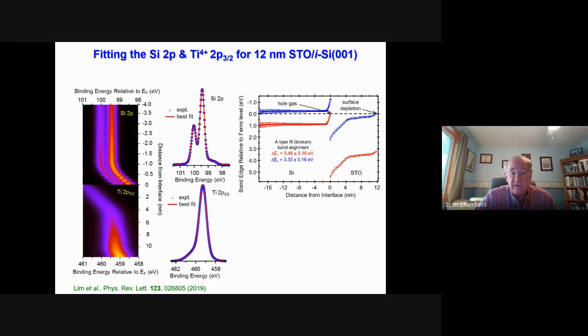We just take the difference in potential between the silicon valence band maximum and the STO valence band maximum, or we could do it for the conduction bands as well. We just take that difference right at the interface, and we find that we have what's so-called type 3 or broken band alignment with those band offsets.